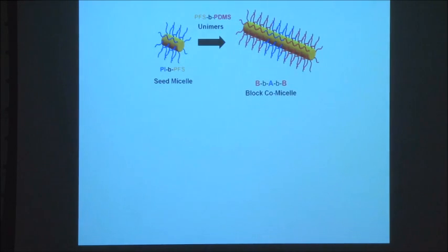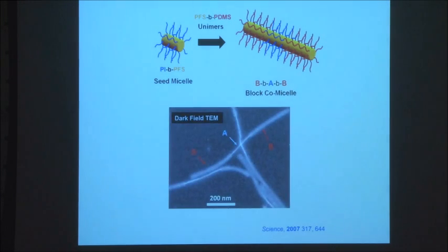So you can make block structures. If you take seeds with one coronal block, so this is polyisoprene in blue, and add unimers with a different coronal block, we've got polydimethylsiloxane in red, you can make triblock comicelles. So this is a BAB triblock comicelle. And if you do careful electron microscopy, you could actually visualize the different segments in these structures. So the A block here is polyisoprene in the middle here, and B block, which looks thicker because the corona that contains silicon scatters electrons. You can see here, and you can do this type of approach to build up really quite intricate structures.